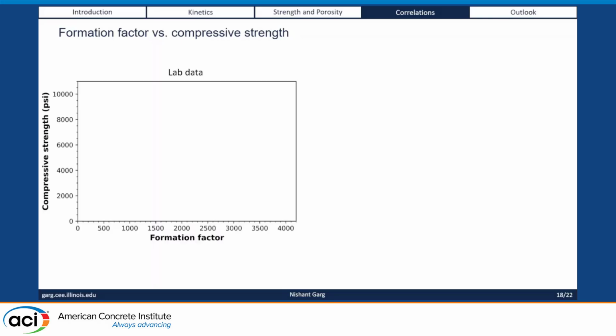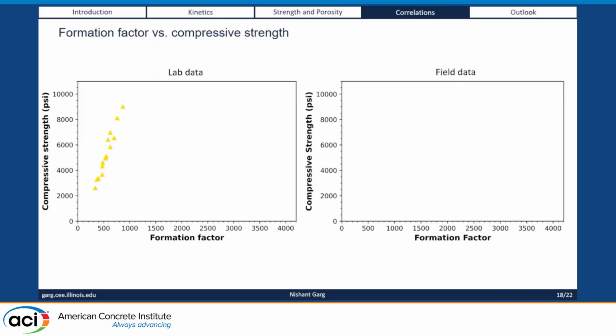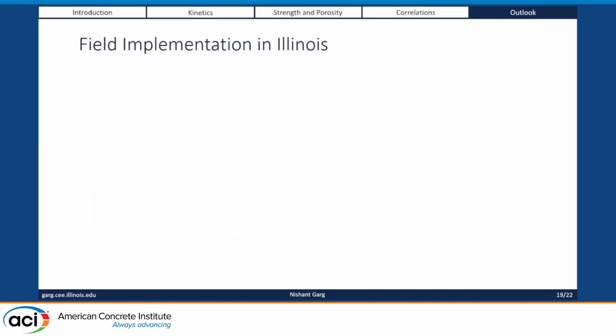The other thing the DOT was really interested to explore was to compare formation factor versus compressive strength. And there were some interesting things we learned: if you look at the lab data, you get almost a linear correlation between the two. But if you look at the field data, it's a little bit all over the place. And our hypothesis here is that you have a cocktail of admixtures in the field, and there's the curing condition and so on. There's a lot of variation there. But generally, if you look at individual mixes, it does have a specific trend.